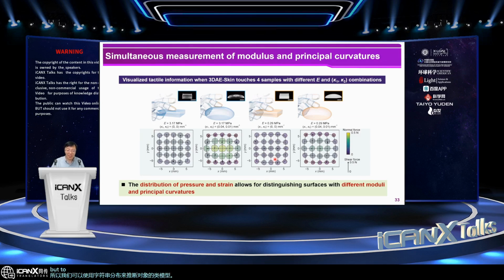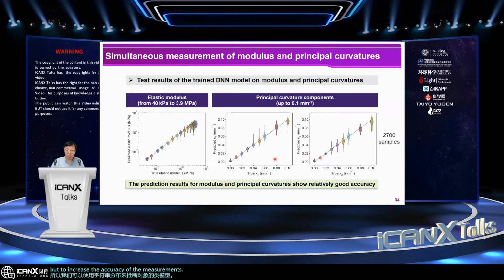But to increase the accuracy of the measurements, we need to establish a deep learning neural network model for this purpose. So actually, we have developed this kind of DNN model to establish the mapping between the elastic modulus and the two principal curvature components with the relative resistance change of 240 sensors. And actually, the database is very important. So in our case, the database was constructed by using the E-skin to touch a large diversity of samples with 51 different shapes and 15 different elastic moduli.